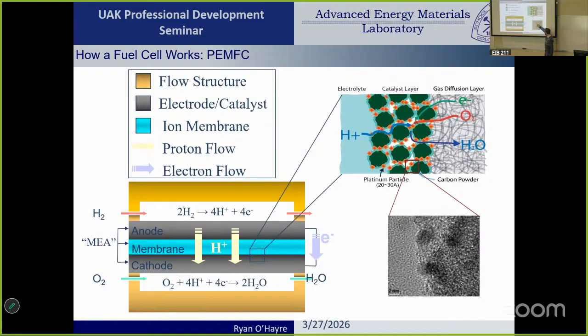And in fact, these little tiny darker dots, those are the platinum nanoparticles. And they're sitting on top of this kind of bigger structure. That's the particle of carbon. And you can even start to make out the lattice, the individual crystal lattice fringes of the platinum atoms in those particles. So we're almost zooming into the atomic level.